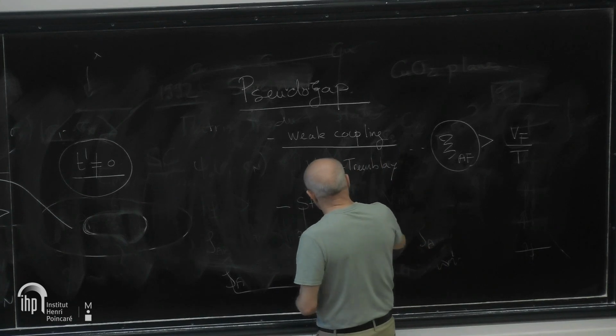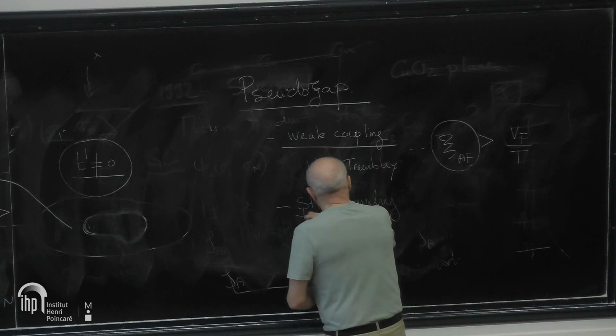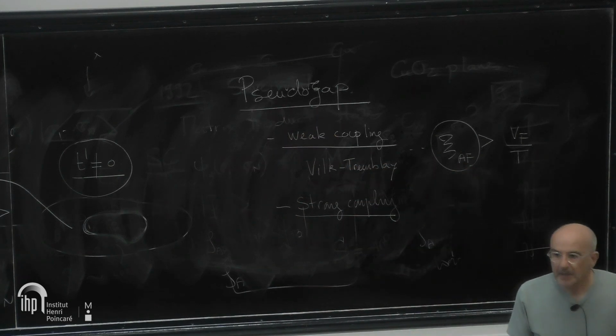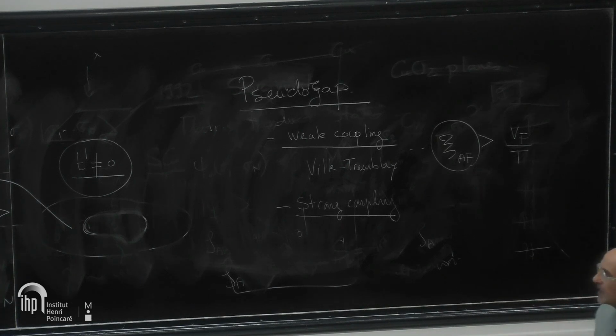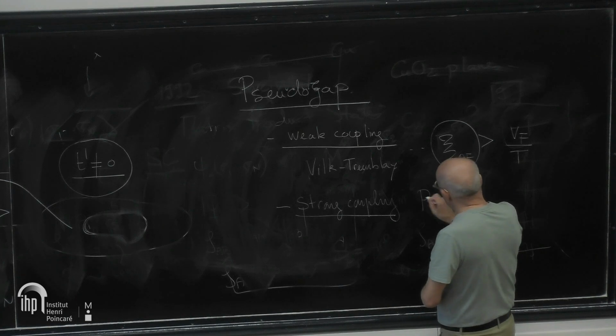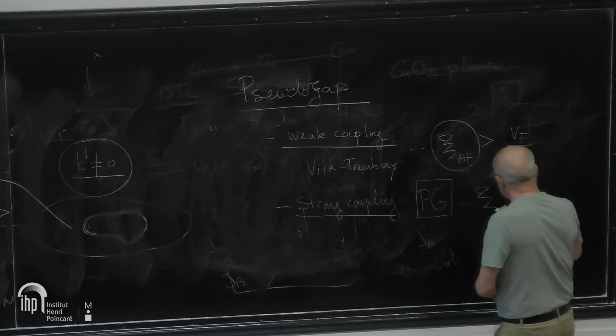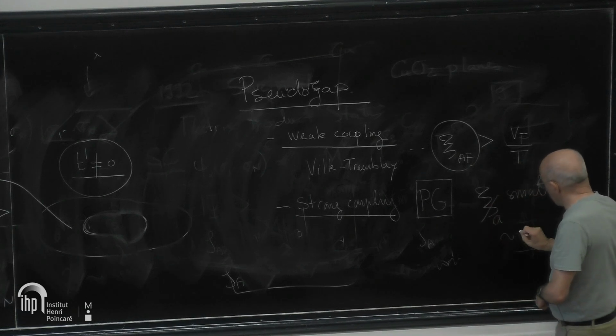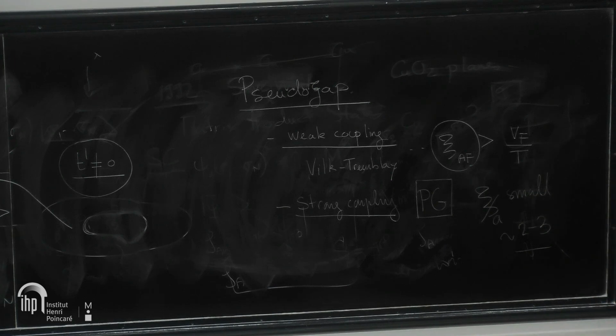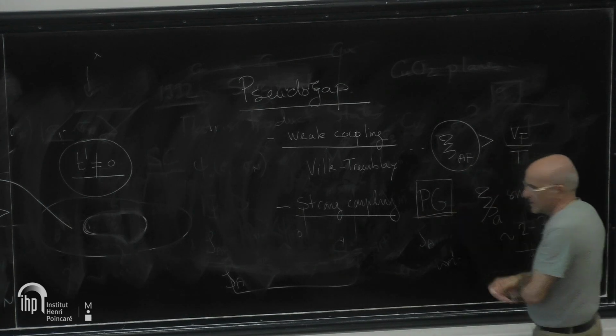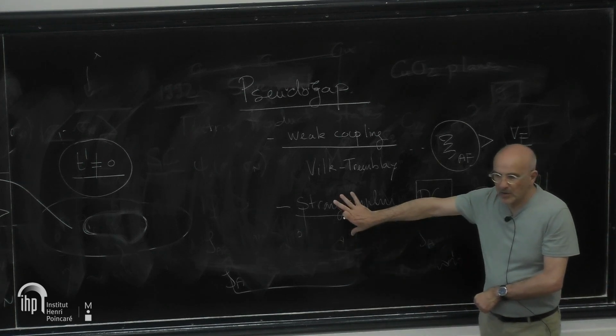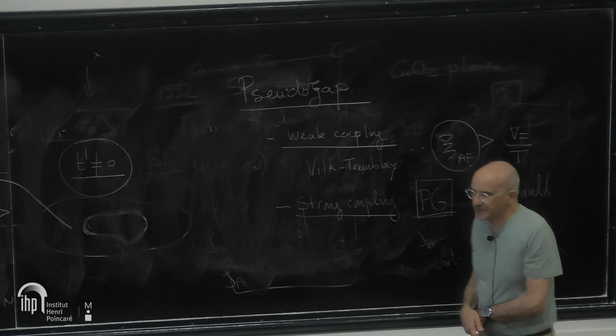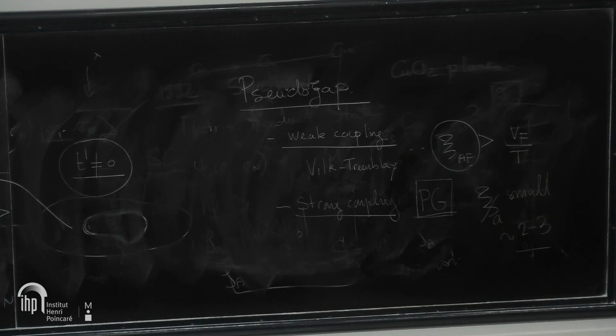Now at strong coupling, quantum embedding methods first, then diagrammatic Monte Carlo methods, and also finite temperature extensions of DMRG have established that a pseudogap can appear even in the regime where xi is small. And xi is small, meaning xi over a is of the order of 2 to 3 lattice spacings. So it doesn't need to satisfy this criterion. And the picture of the system, if you want, is small bubbles of antiferromagnet, or perhaps even just singlets, with holes moving in between. And this quantum fluid has a pseudogap. So this is now seen by basically all computational methods. It started with quantum embedding and DMFT, but it's now very well established. Okay, well, that's it.